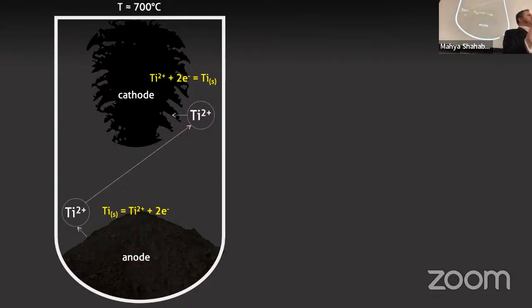But in its most simple form, the electrorefining process is: you oxidize the titanium out of the anode, it transports over to the cathode, and you do your reduction there. A certain number of materials are rejected into the anode, another set of metals are rejected into the salt, and there are some that you have problems with, such as iron and aluminum, and they're rejected by never seeing them. They actually saw a difference in purity based on the baskets used in Salt Lake City to collect the sponge. So just physical contact with the sponge, by changing the baskets, showed all the way into the final product coming out as a sputtering target. So there are certain things that once they're in, you can't get them out, even with this process.